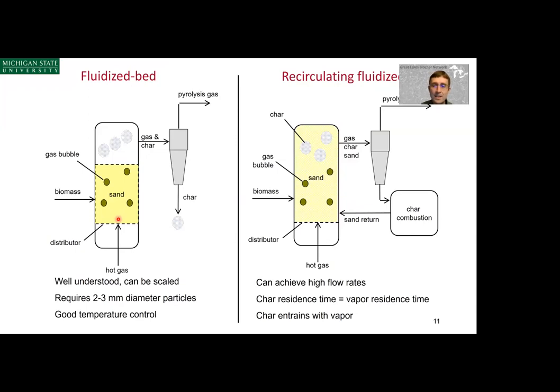So what that means is the char comes out with the sand, which in the case of a recirculating fluidized bed comes overhead with the gas and char. Then the char and sand go to a char combustion unit where the char is combusted in the presence of the sand to reheat the sand.